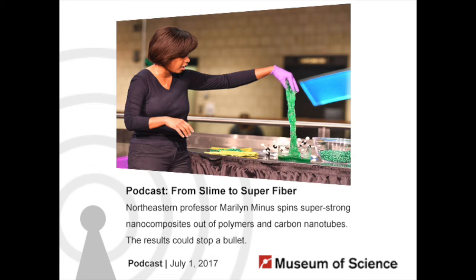Okay, so a couple things there. The direction you want them to be, you want them to all be kind of parallel to each other. Is that the direction? Because I make fibers, I want them all lined up and parallel with each other, but I want their strands to run along the length of my fiber. So I'm aligning them in the direction of the fiber, trying to get them all to line up. I use temperature to get them to want to line up, and then I use flow to push them in the direction of the fiber. So what do you mean by flow? Are you flowing water or a liquid over them? I'm flowing a liquid, but it's a process that we use to make fibers, which is called spinning. Spinning is a process that's typically done in some kind of solution.